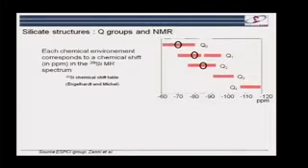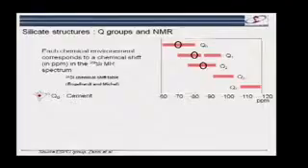Solid-state nuclear magnetic resonance is really the tool that has enabled us to understand CSH well. This has all been done in the last 30 years. It's well established that the number of silicate groups a silicate is attached to determines the position of the resonance peak. We start from what we call Q0 groups, which are present in C3S. This is silicate which is attached to no other silicates.